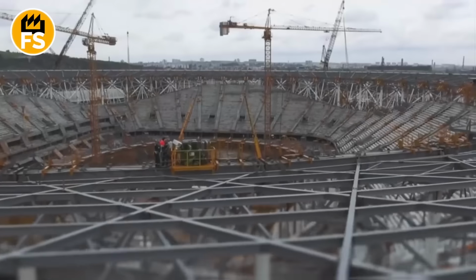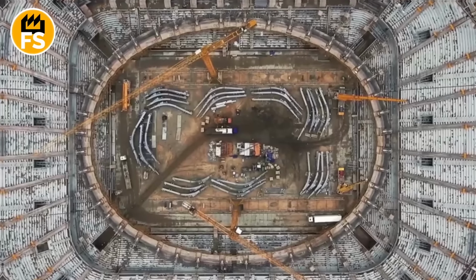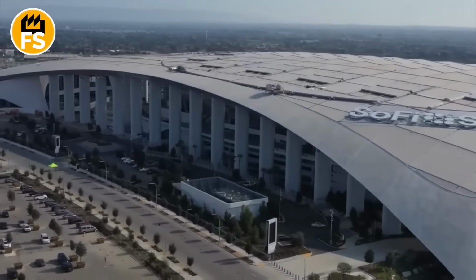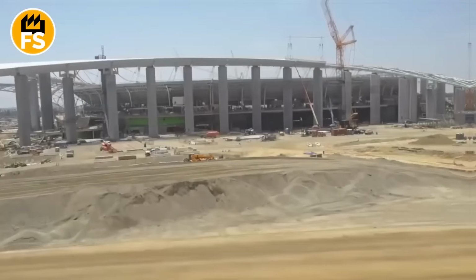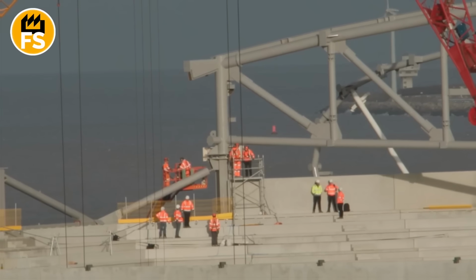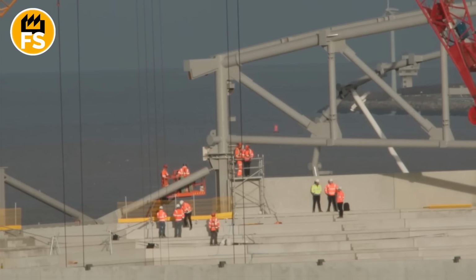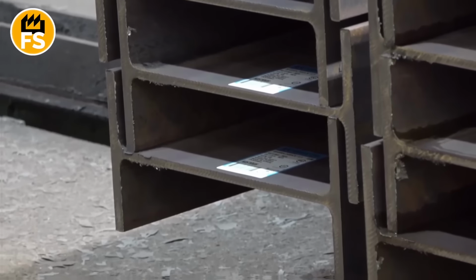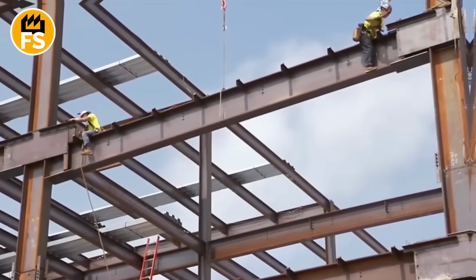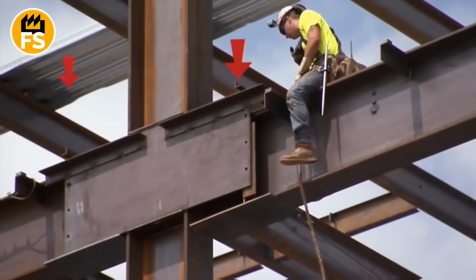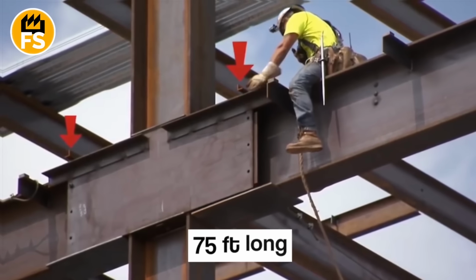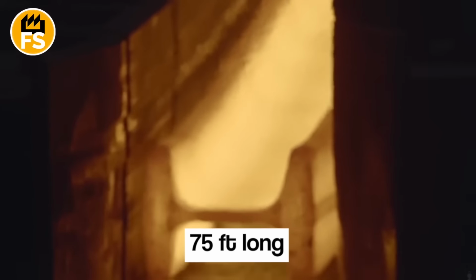For SoFi Stadium, they needed beams ranging from 14 inches deep for smaller supports all the way up to 44 inches deep for the main roof structure, and each size requires a completely different set of rollers. The precision required here is absolutely critical, because these beams need to be accurate to within 1/8 of an inch across lengths that can be up to 75 feet long.